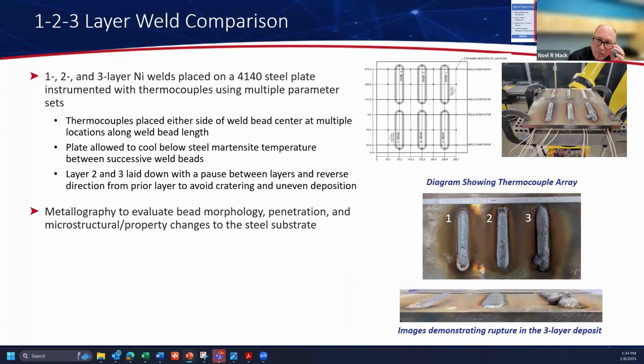So we then put this into the physical, and here you can see a snapshot of the inside of the cell that this was built on, the top right graphic. Here we put down 1, 2, or 3 layers of nickel welds on this 4140 steel plate. We've got thermocouples on either side of the weld beads so we can understand the thermals. We also have a cooling channel underneath so we can control the cooling, and we like to cool below the steel martensite temperature between the successive beads, so we actually put a delay in the weld strategy.